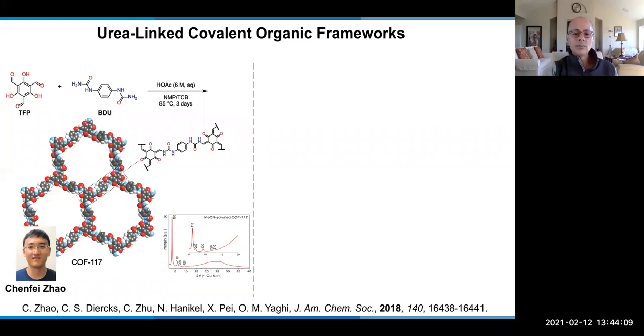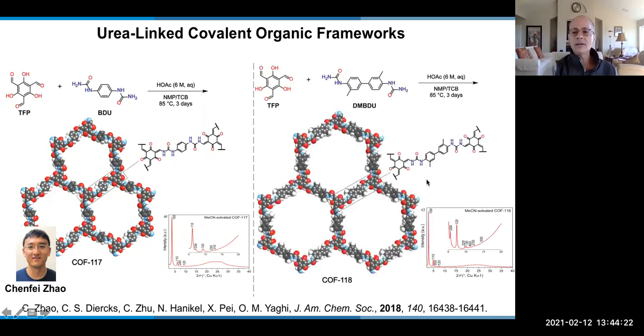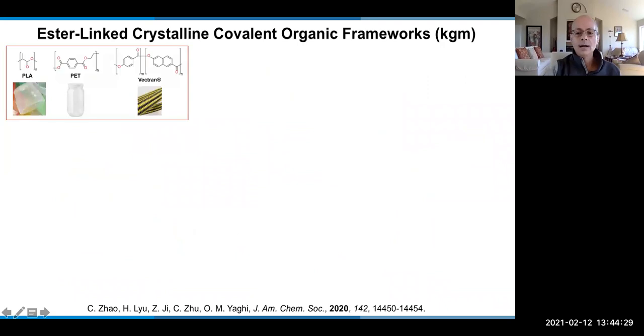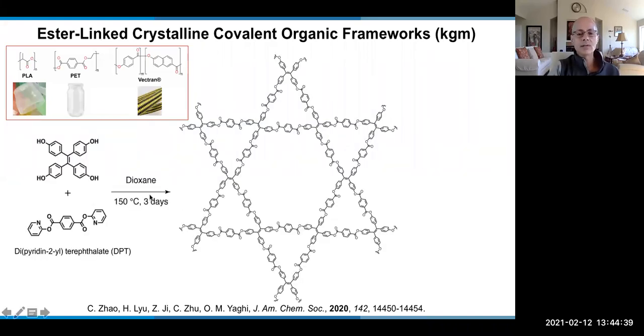And recently we've shown how you can make urea-linked COFs. See here the high crystallinity of these COFs, as well as Chenfei has been able to extend this by using longer linkers and still crystallize the COF. Also, Chenfei was very successful in taking a linkage like the ester linkages that are so useful in polymers and making COFs out of them. Here he's using dioxane, not mesitylene, and heating a little bit more for 3 days.